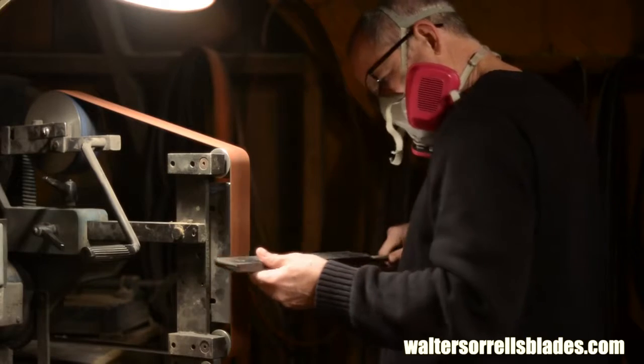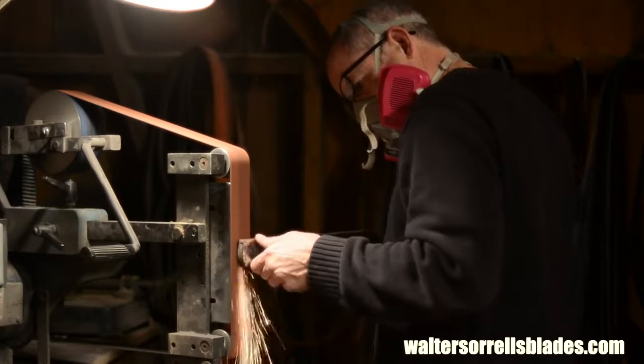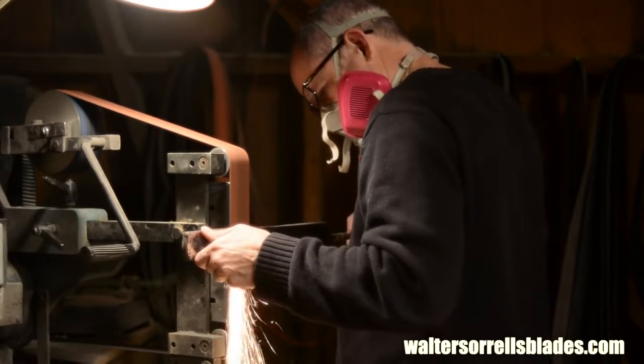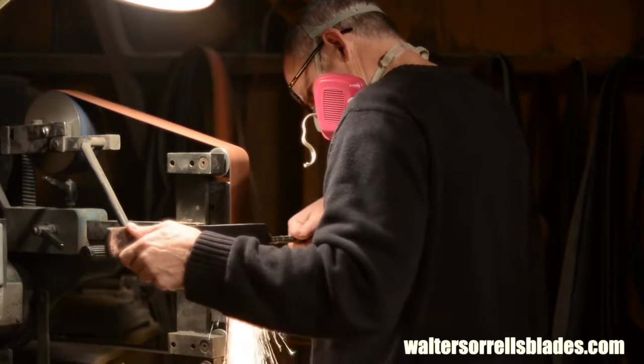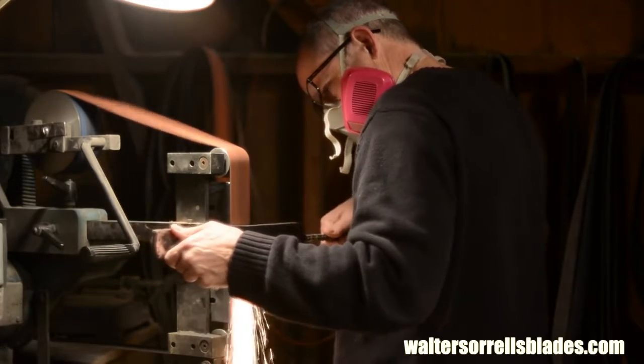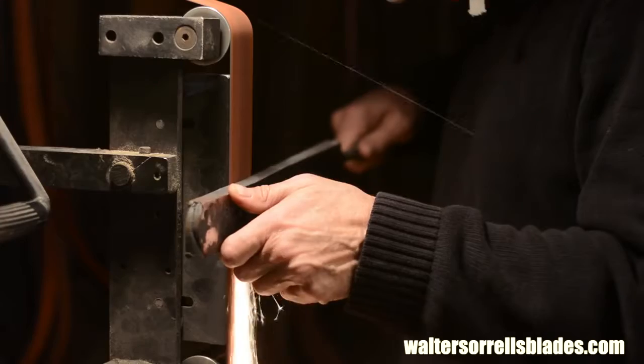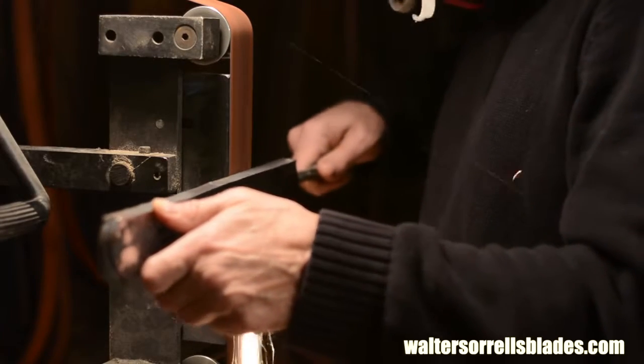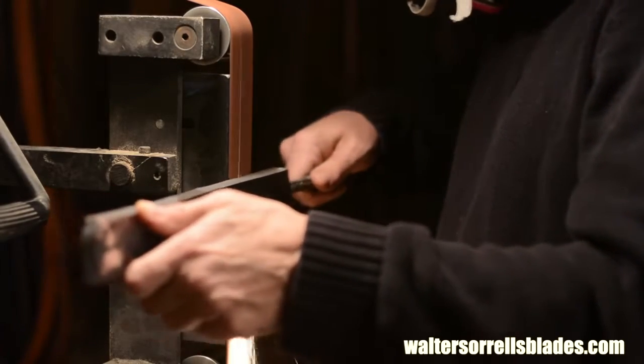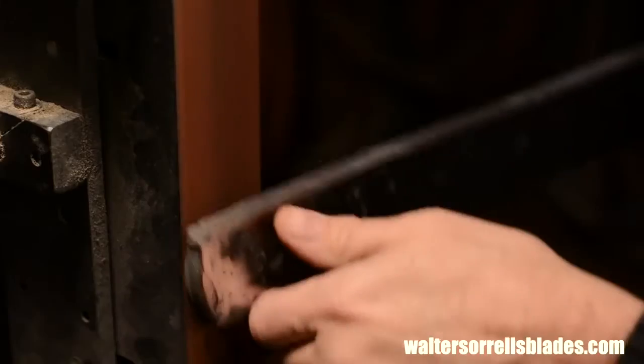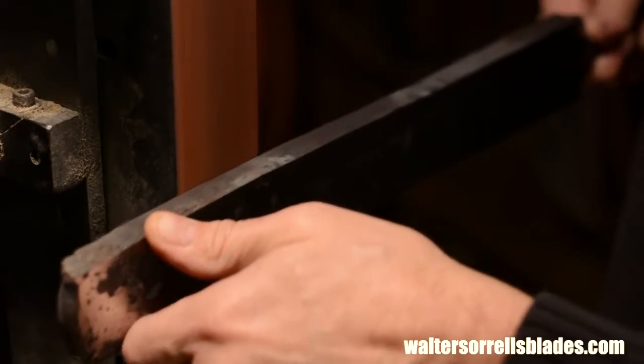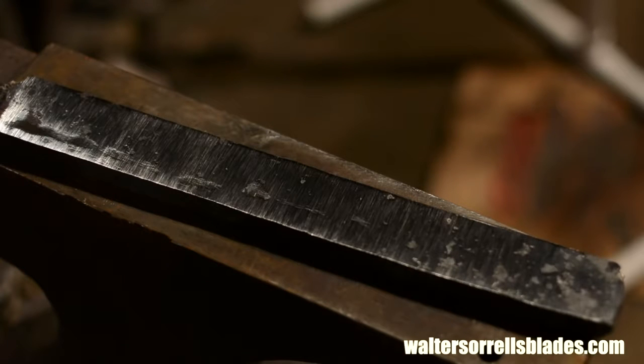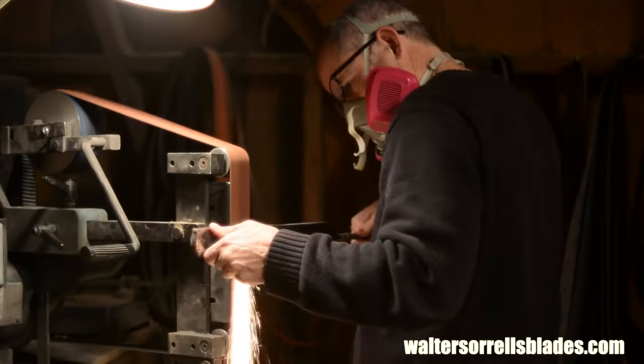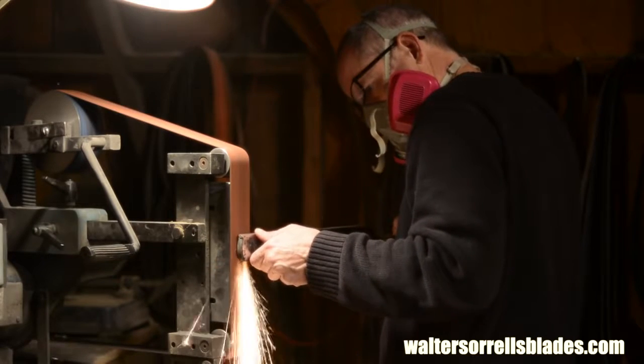What I'm doing here is basically the same approach I took with the original bar stock. Dead clean and as close to dead flat as you can get. Be very strict here and make this thing clean, clean, clean. Do whatever it takes. One little bitty piece of scale left on the face there can leave a divot that will turn into a problem weld, and then that'll stretch out and it can be a very big, long, ugly inclusion that will ruin your blade. If you have to grind a little extra, so be it.